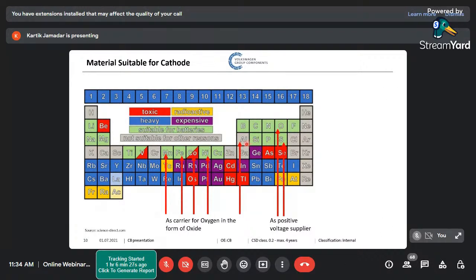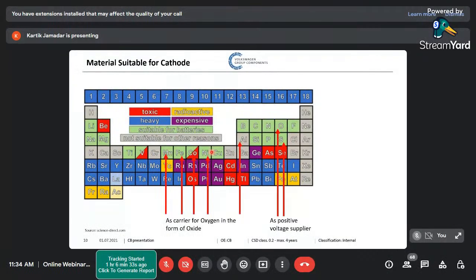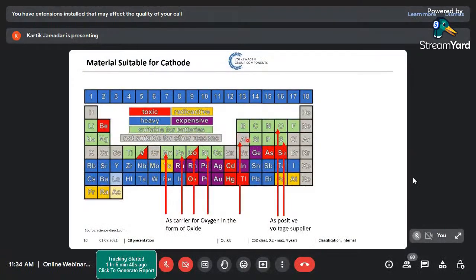Tesla is using it without manganese. They are using a much riskier, say unsafe, technology. In that sense, I would say they have 85% nickel, 10% cobalt, and 5% aluminum. And there's no manganese, which can give good stability at high temperature. But that's why they are going with small cells, because a small cell has less energy inside anyway. So even if one cell would have a problem, the complete cell pack would not get a problem. But it would be unwise to go with the same chemistry for big cell dimensions.